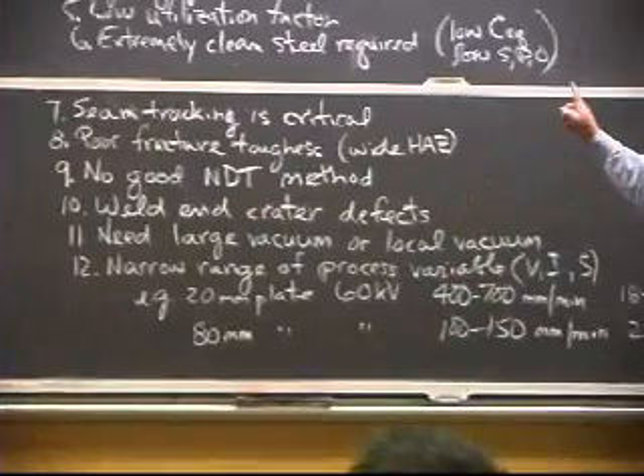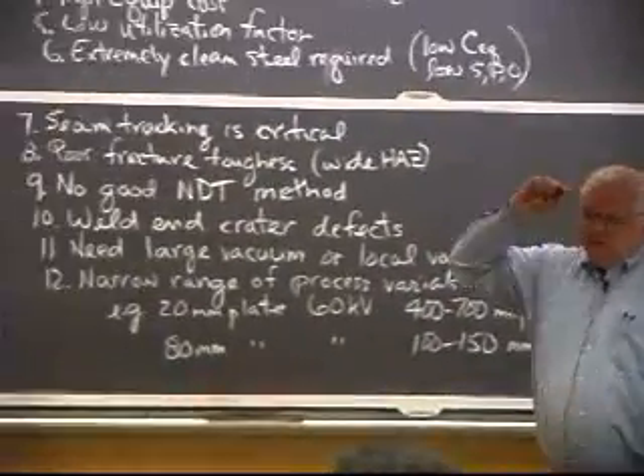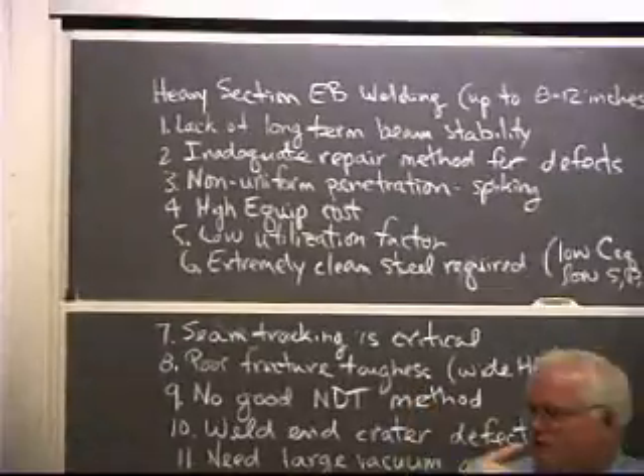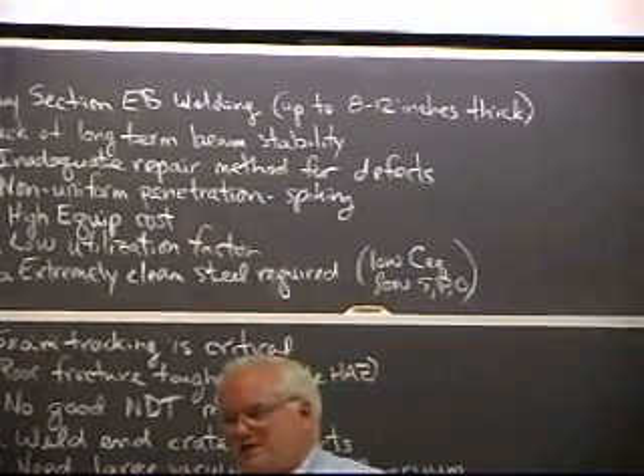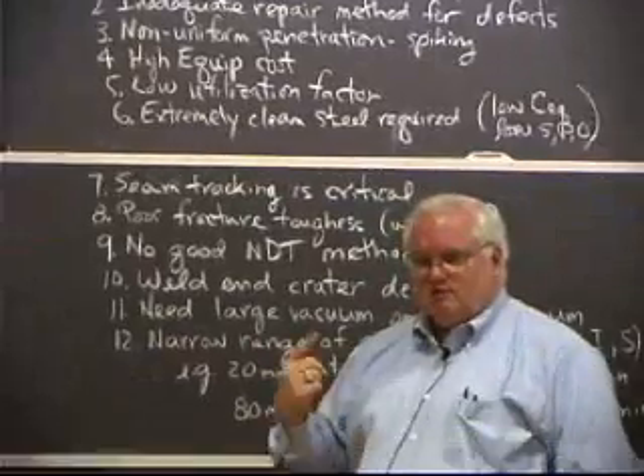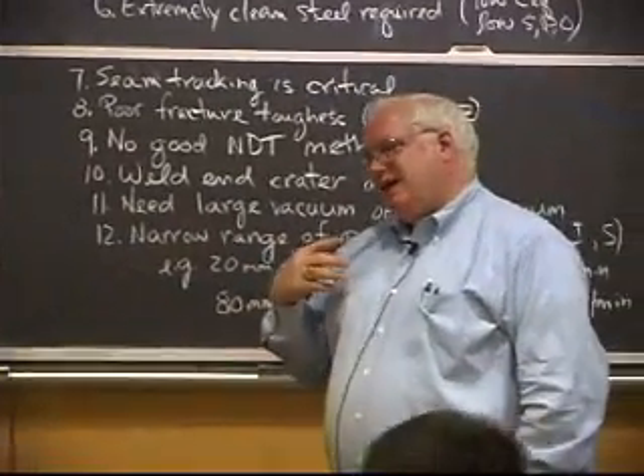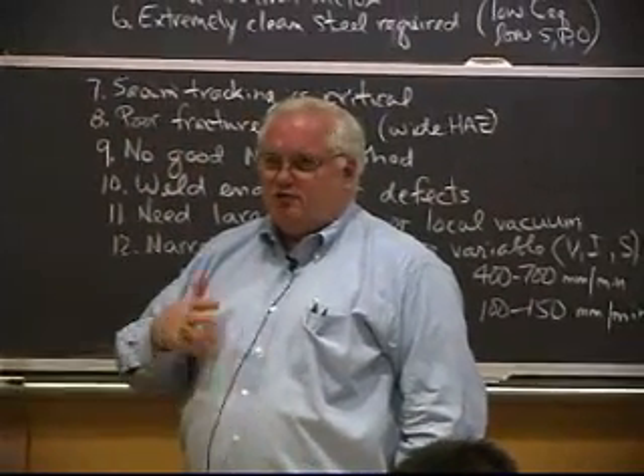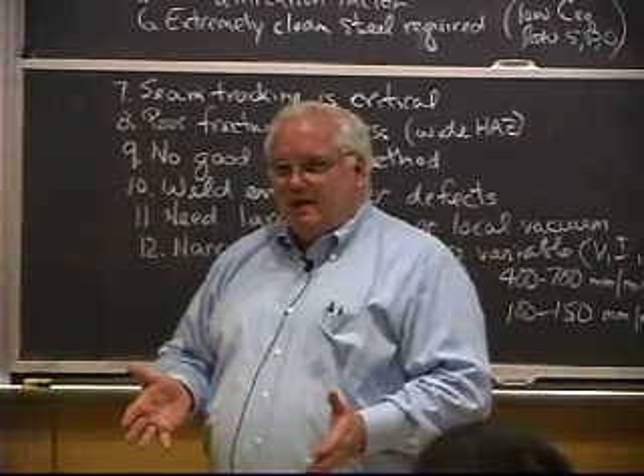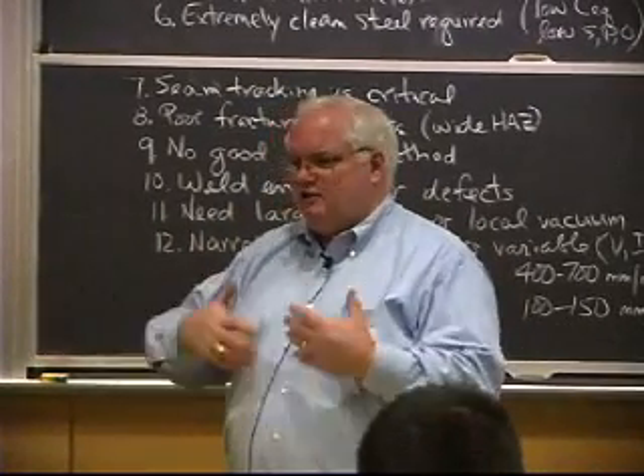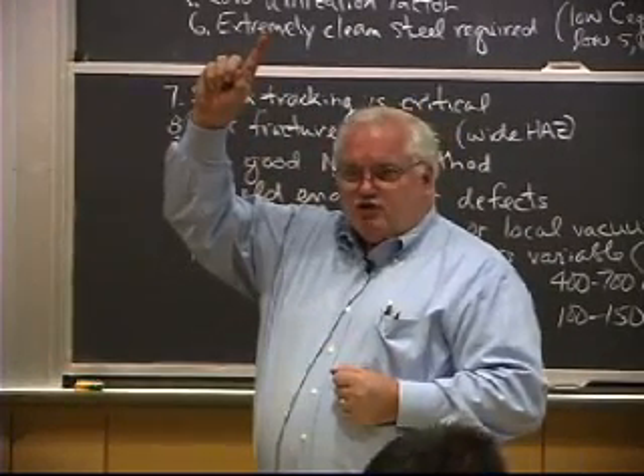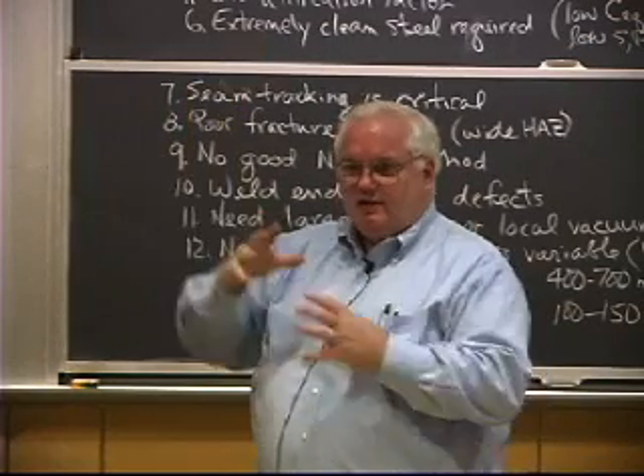Anyway, one of the problems they have is lack of long-term beam stability. If you're going to weld one of these things going around at the type of speeds we'll get to down at the bottom, it takes about 30 minutes to go around to make the circumferential weld. Well, it turns out about once every 10 or 15 minutes you'll get a spike in your power supply, and you'll lose your power, and you'll lose your beam, and you'll create a defect because you lose your beam hole, okay? And it was kind of an intermittent thing. It had to do with vapors in the beam. It turns out the vapors coming out of that weld pool are electrostatically attracted right up to the gun. And if you get too much metal vapor up in the gun cavity, you'll get an arc over.